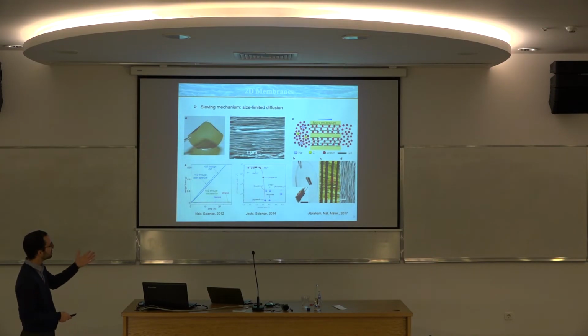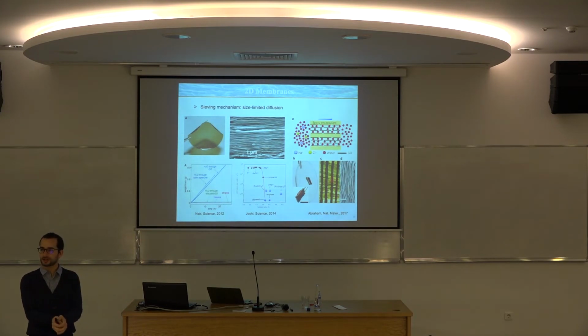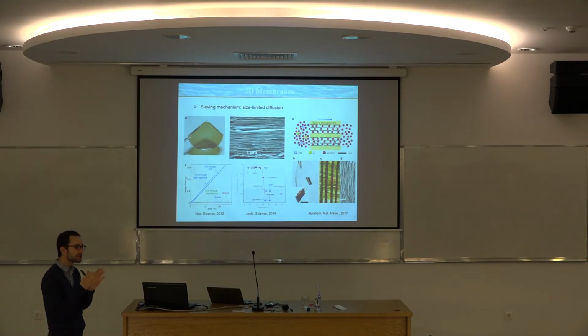The main problem with this membrane is graphene oxide is very hydrophilic, and the water will just penetrate in the capillaries, swell, and then you lose the spacing between the nanosheets. And at the end you lose the control of the sieving. So the approach, actually the same group more recently, 2 years ago, they proposed to control the swelling by encapsulating this membrane in epoxy. So they use an epoxy matrix to encapsulate the nanosheets.